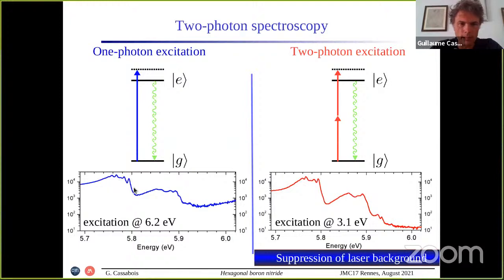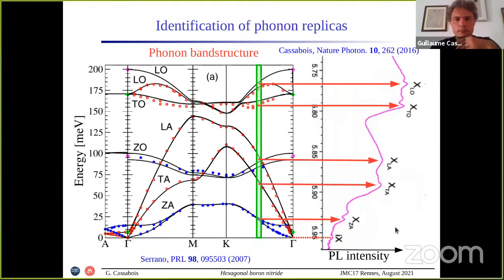We recognize some bands and backgrounds due to the laser emission. To get rid of this stray light, we perform two-photon excitation, using laser light around 400 nanometers. By absorption of two photons, we can study the emission spectrum without any stray light from the laser. We decouple completely in the spectral domain the emission and excitation of the semiconductor, and by doing this we could resolve new lines, which was key to understanding the emission spectrum of HBN.